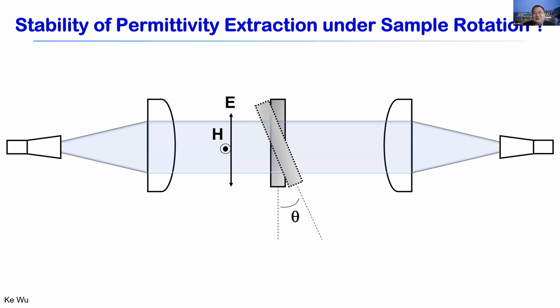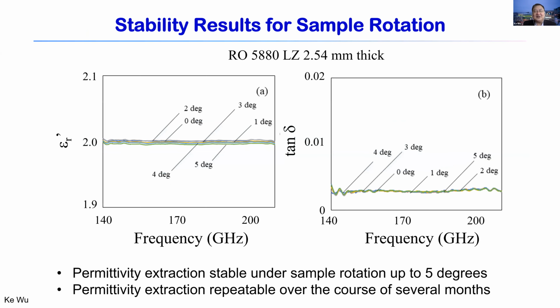At the same time, the lens measurements give us something interesting. If the sample is rotated a little bit, let's say inclined, we can still make a good measurement. For example, in this case the rotation angle is up to 5 degrees. We can see the measurement result still remains quite constant over the frequency of interest. This is the D band. So we feel these are very robust values, even when the sample is not very well placed. In this case, measurements still give you very nice results.